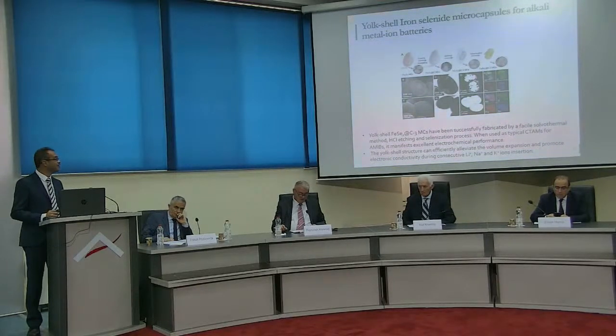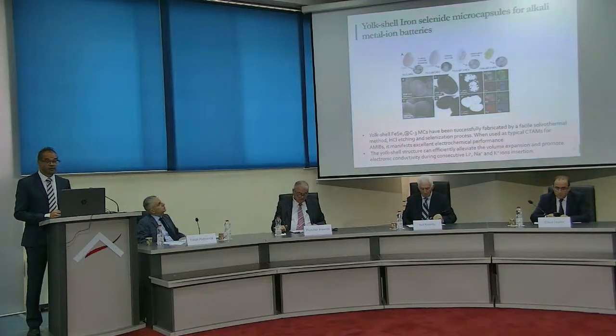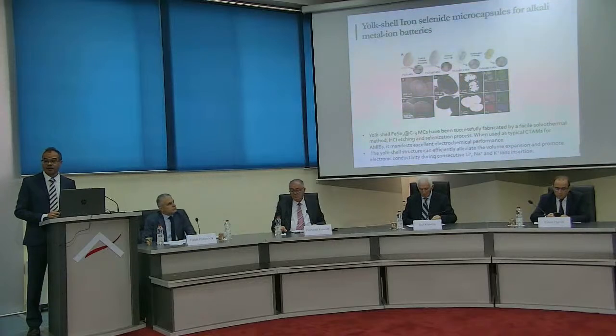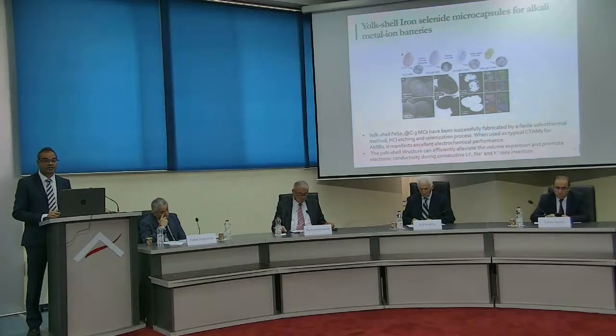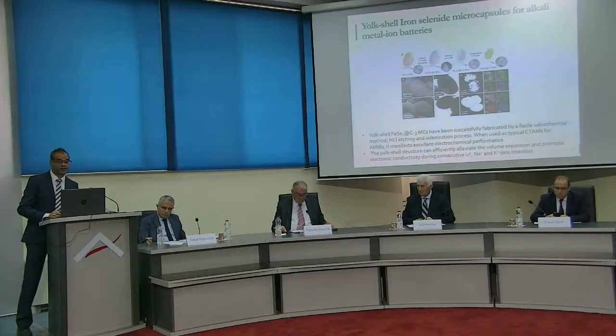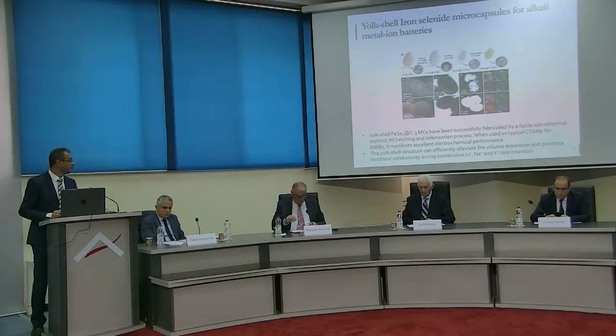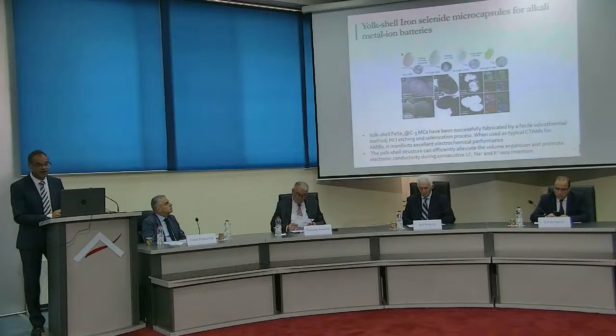So what we produce is a spherical structure of oxides, usually, and then we leach the oxides by sulfuric acid or hydrochloric acid or anything, coated by carbon, usually polymeric carbon, and then carbonize it under nitrogen or argon to form the hard shell that we want, and then selenide it or convert the oxides, if we want, to any other structure, such as, in this particular case, the dichalcogenides, or some carbides or some nitrides or phosphides, different structures really, and different types of compounds that we did really try. Probably over 30 compounds we tried in our lab in yolk-shell structures.